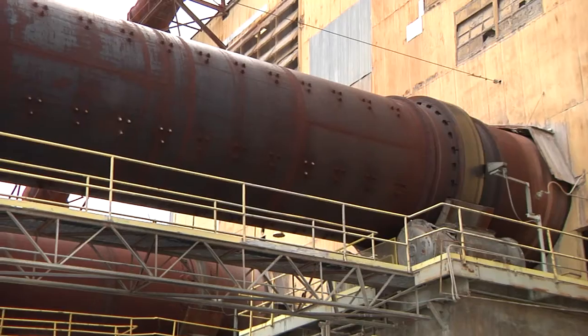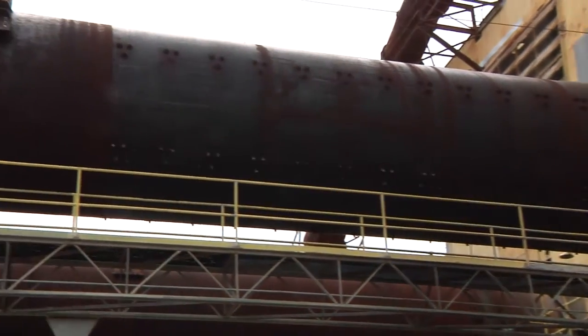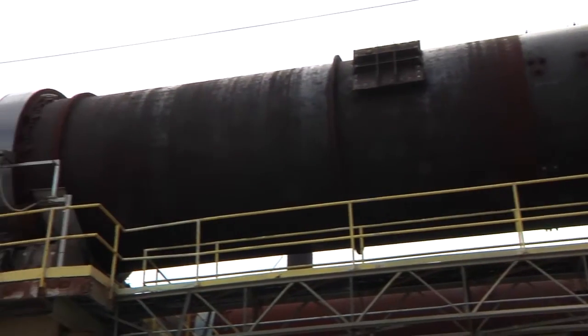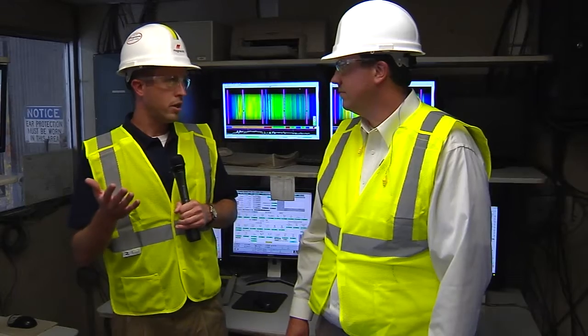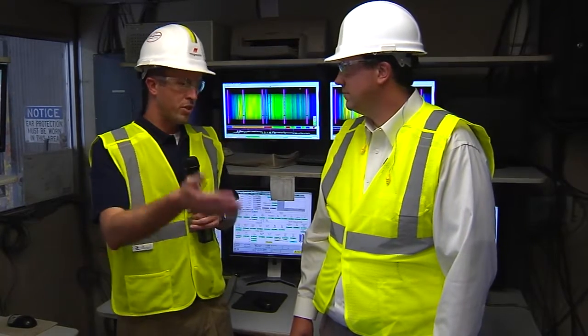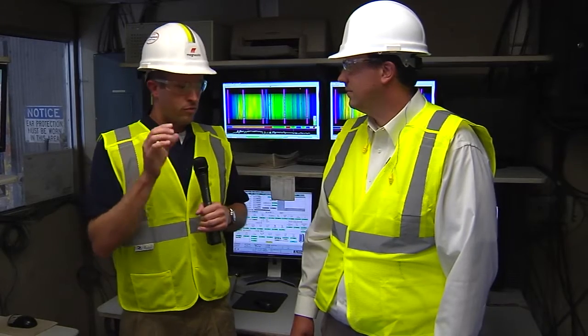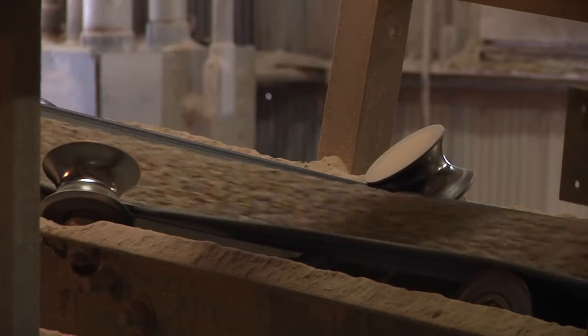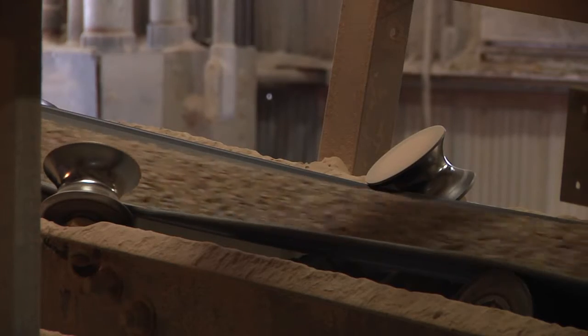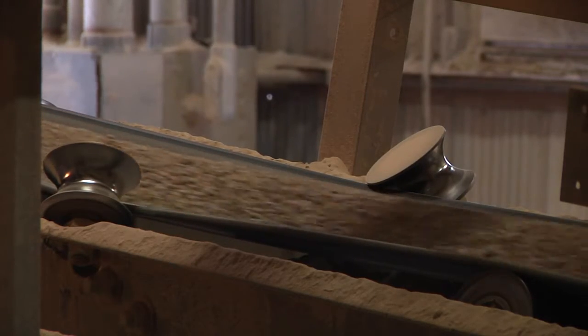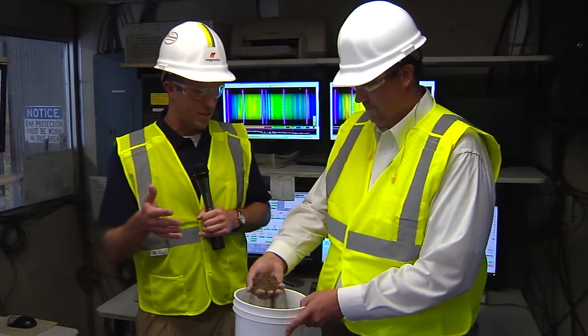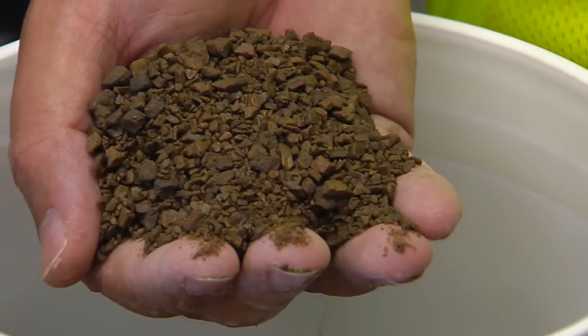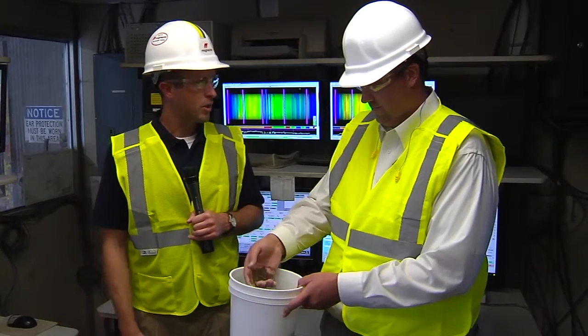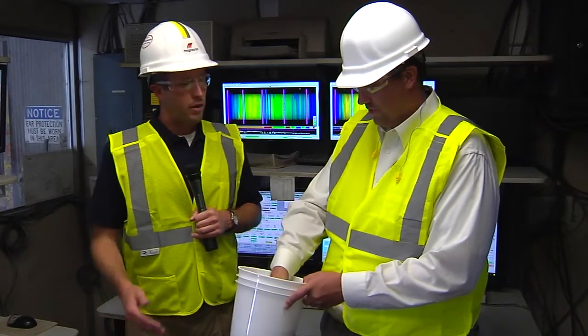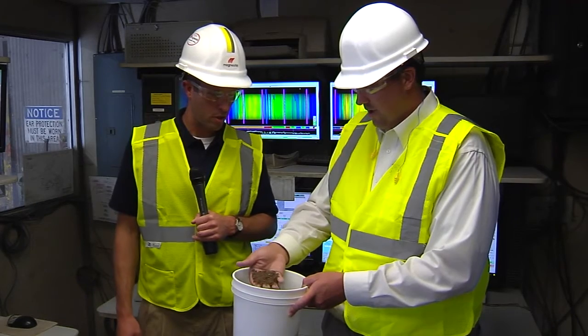It spends about 6 to 8 hours in the kilns, reaching a peak temperature of about 3,500 degrees Fahrenheit. So very, very hot, the hottest running rotary kilns in the world. That hot temperature is required to drive off the CO2 that's inherent in the stone, and to create that dense dolomite sinter that we talked about. When that sinter comes out of the kiln, it's at about 3,000 degrees Fahrenheit. It is then cooled and placed into bins, where it is later processed more and used to make the refractory products that we'll see in a little bit. Wow, you can see the dark brown color of that.